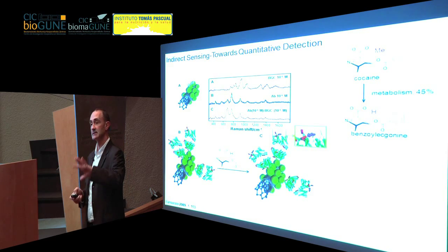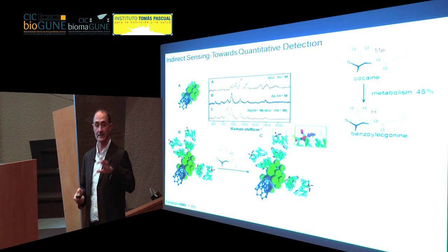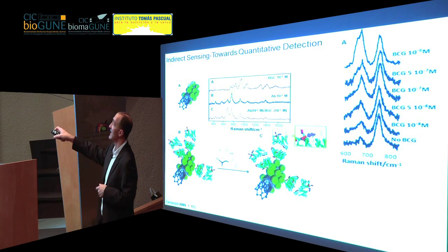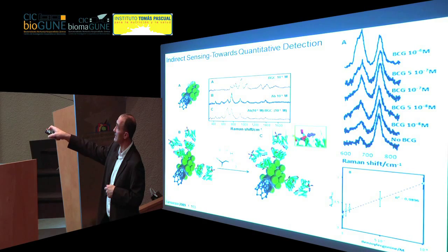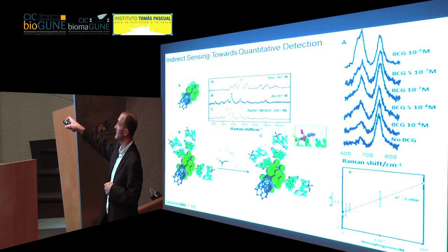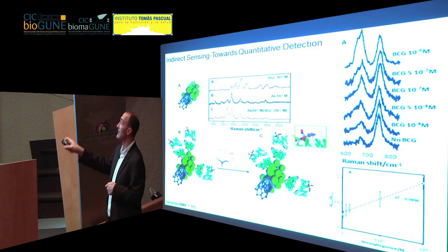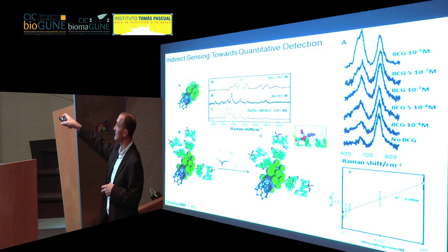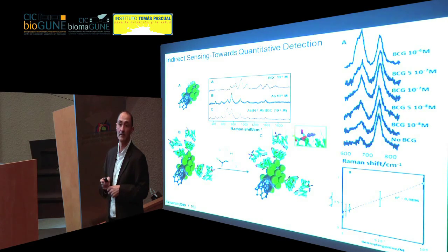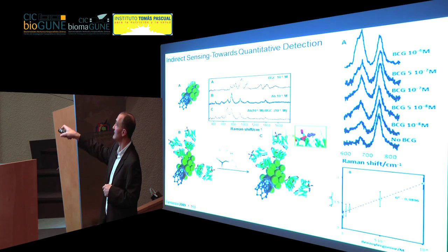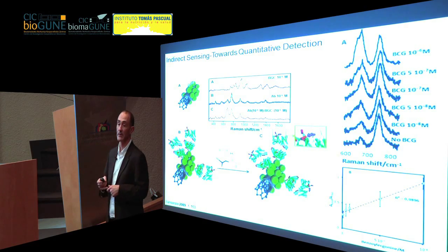So it's the change in these peaks that tells us about the attachment of the molecule to the antibody. And lucky enough, if you watch carefully, this peak remains constant. So we can use this peak as an internal standard, and then, comparing the ratio between the intensity of this peak, which gets increased in the presence of the analyte, we can compare the intensities and plot a calibration curve to find out the concentration of the analyte in solution.